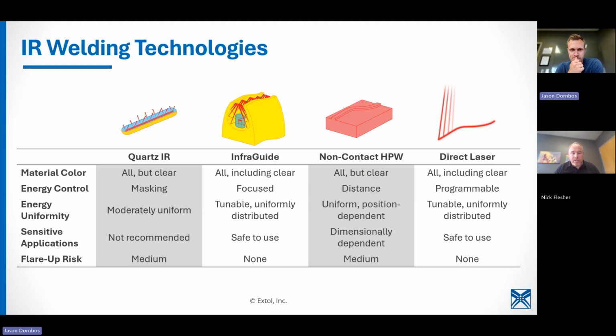But I would say, generally speaking, direct laser is probably the fastest, maybe comparable to InfraGuide. Quartz is probably next from a speed standpoint, and then non-contact hot plate welding can generally be the longest, slowest for melt time. Seal times for us typically are all the same. We try to do 5 seconds. Sometimes you might have a part that needs to be sealed a little longer. But let's compare across these technologies just as you run across them: Quartz IR, InfraGuide, non-contact hot plate welding, which is basically like hovering.